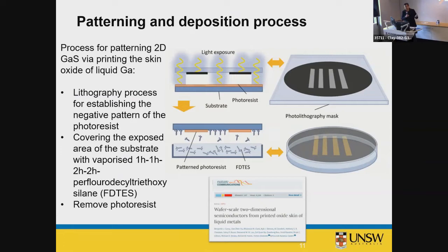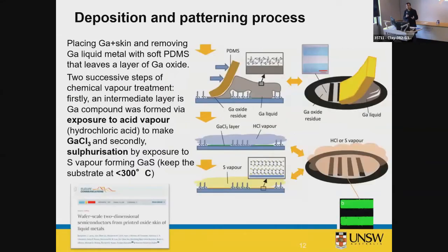It's very simple. For instance, the example here, you put photoresist there, you put a mask, develop the photoresist, the areas that are not developed are removed. You can fluorinate those areas and put a droplet of liquid metal, for instance, gallium in this case, on the surface. Oxide sticks to the surface, and we use basically PDMS soft material to remove the liquid metal. You can wash the rest. What remains is gallium oxide.